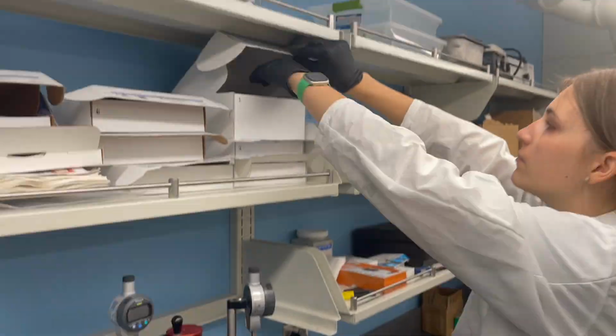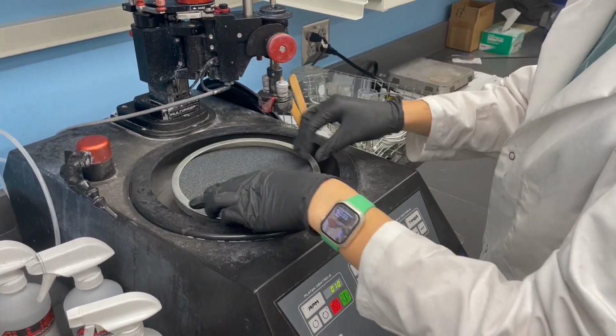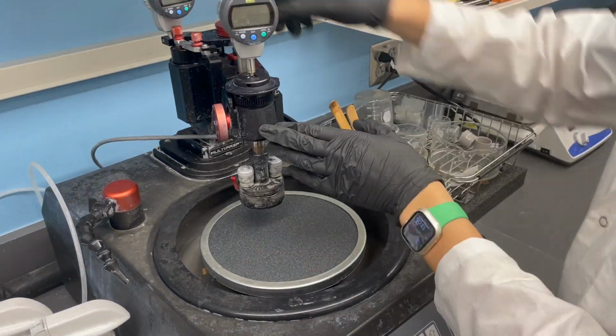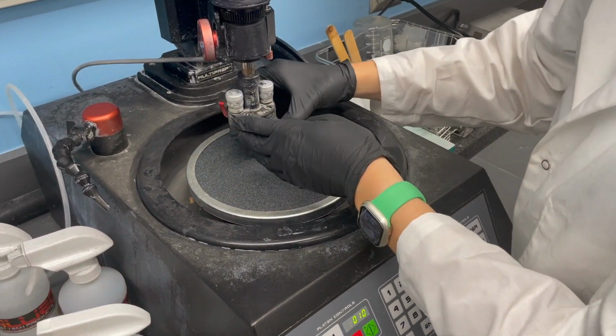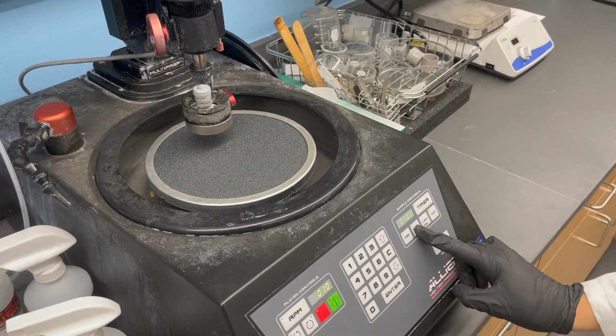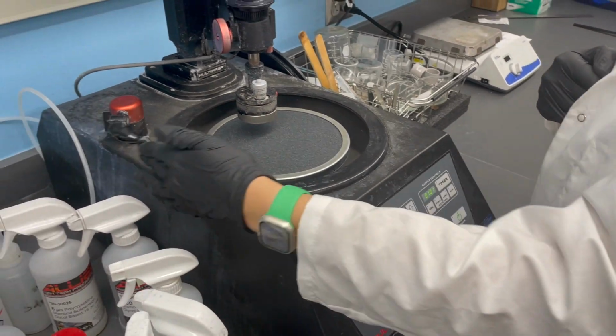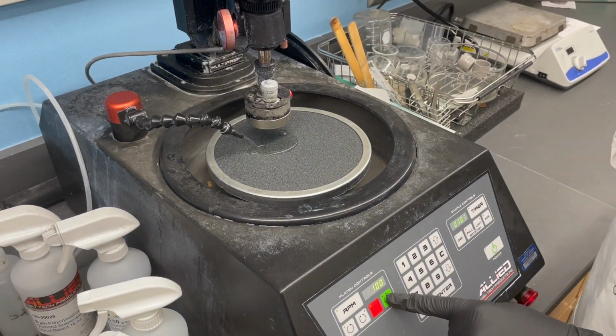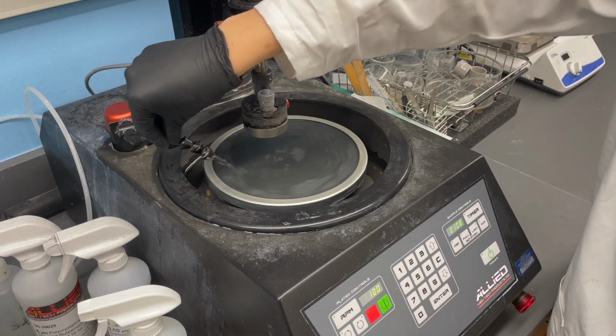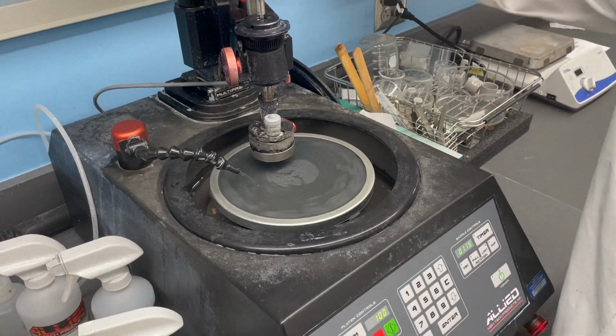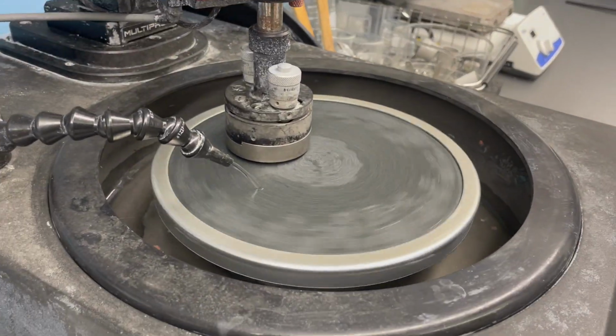Now you are calibrated. Remove the calibration tools and unscrew the arm so you can place your first grit paper. Secure the paper with a silver ring. Take your cooled polishing fixture and attach it to the head with the red pin. Rotate so that the red pin is at 3 o'clock. Set the RPM to 100 and turn on the water to saturate your paper. Lower the head until the sample surface makes contact.